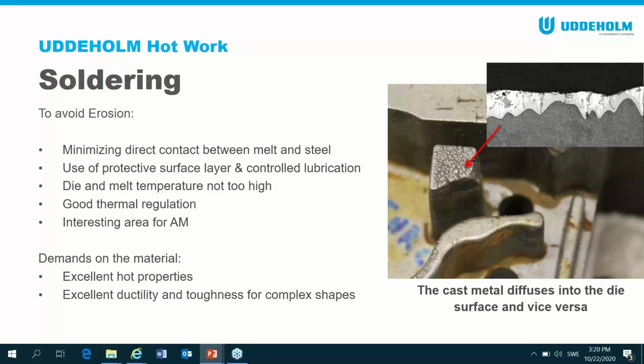And that's where we lead on to really with good thermal regulation. If you use AM on parts like this that suffer this sort of problem, you can really, really improve your die or your production rather, because then this problem area doesn't become such a problem anymore. So AM really is the future. So the demands on the tool steel, at least for soldering, is excellent hot properties, excellent ductility and toughness for complex shapes. And here really we have two materials that you could use today.